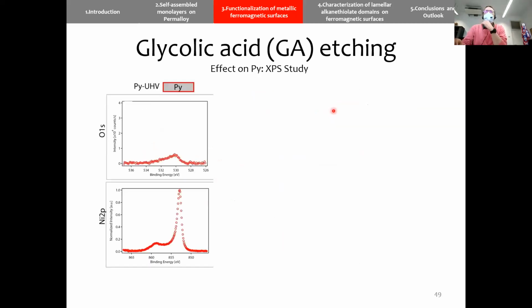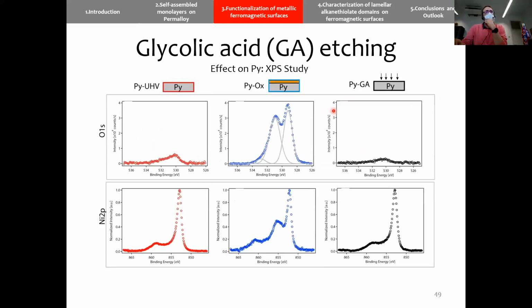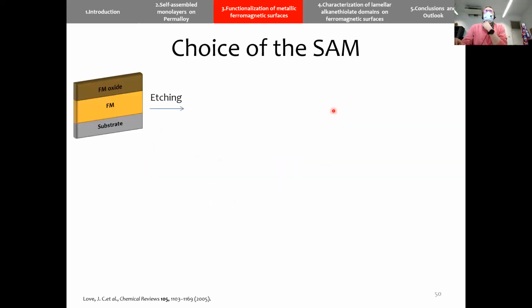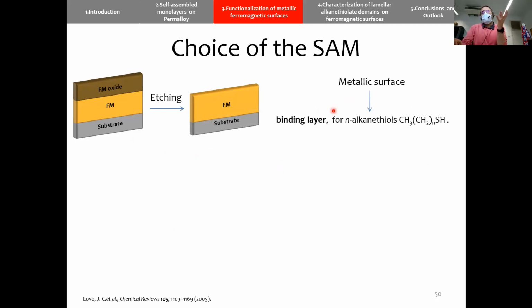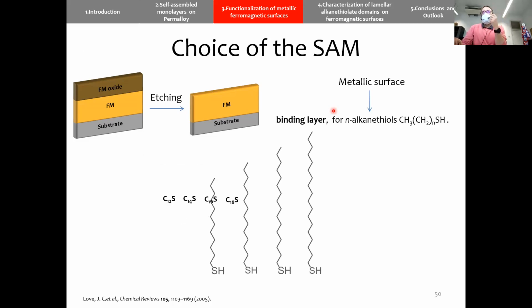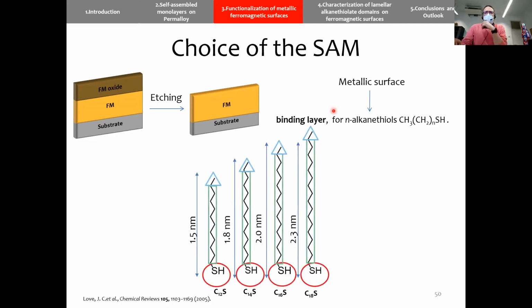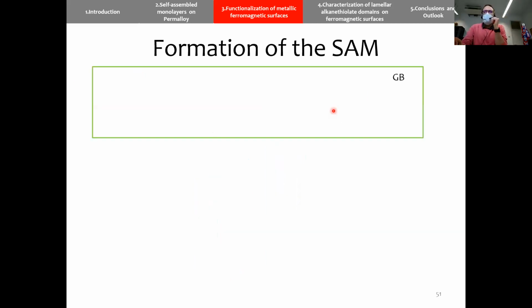And by XPS, we also observe the same. So we recover the metallic surface. So in this moment, we are in presence of a metallic surface. And from the introduction, you remember that I mentioned that thiols or sulfur-based molecules are an exceptional binding layer for metals, showing very high affinity towards metals. And so we also use the same analog family, this time changing from the phosphonic to the thiol group.